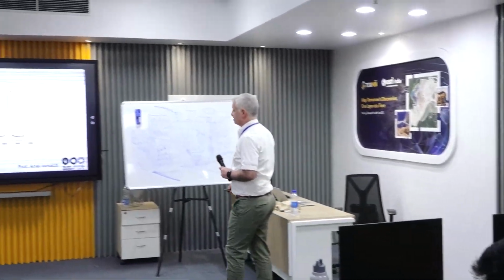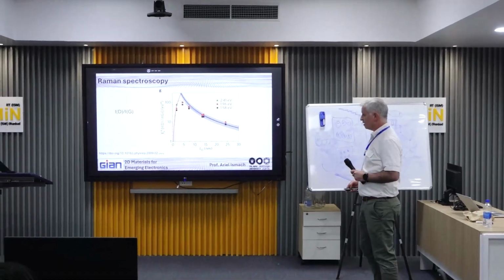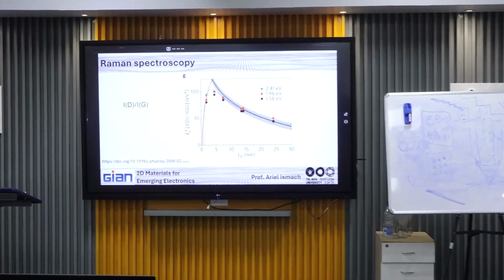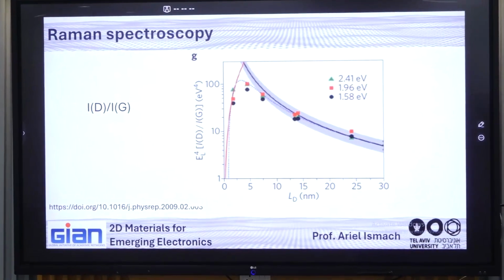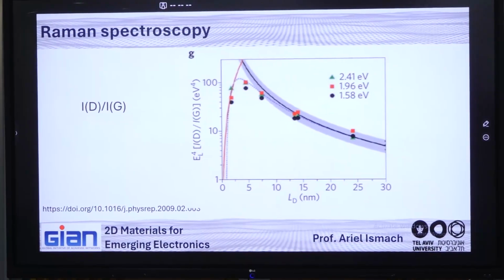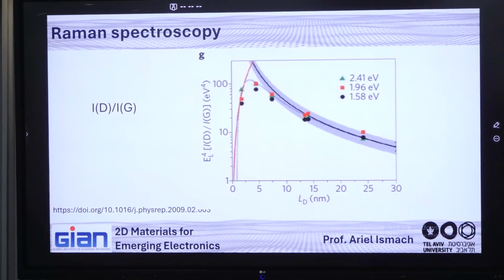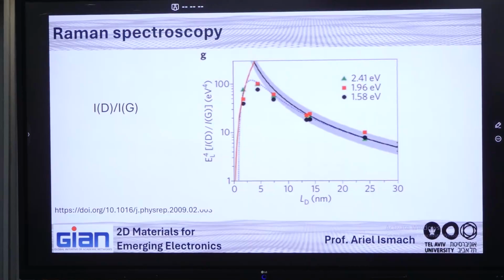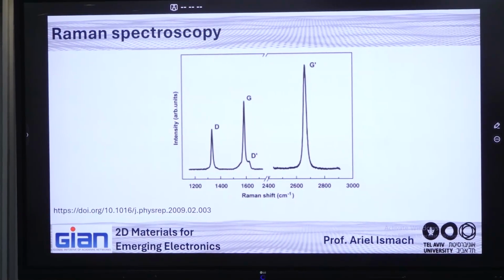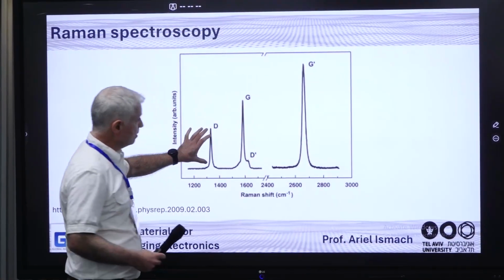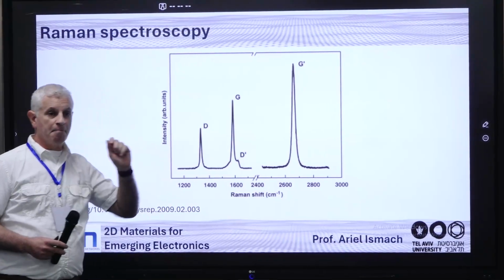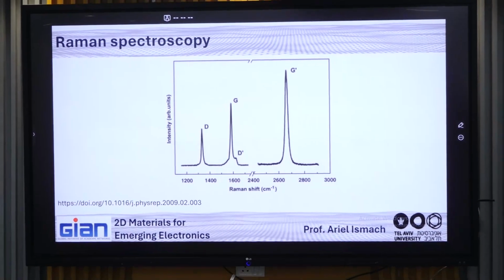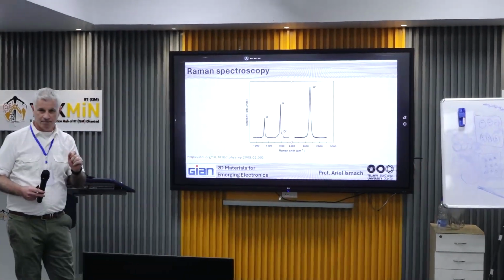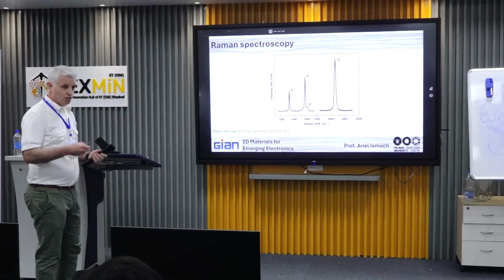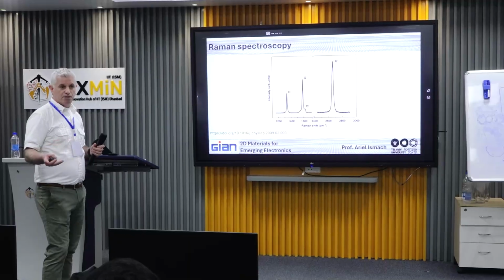Okay. So this is about single layer profile. Now another piece of information, very important piece of information regarding the D peak, is that you cannot compare the intensity of the D peak between different samples just by measuring the intensity of the D peak in this sample and then comparing the D peak in another sample. What you need to do is to compare the ratio between the intensities of the D and the G. And this is a measure of the relative density of defects. It's not quantitative, it doesn't give you a number. But when you compare different samples, it shows you which sample has a larger density of defects and which has smaller.